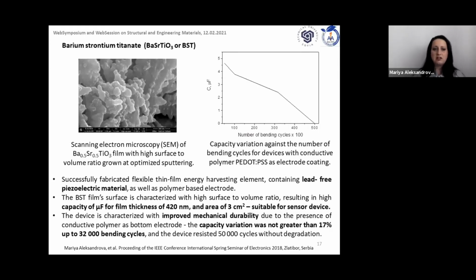The next promising material is barium strontium titanate. We found for this material that it is susceptible to nanostructuring if we grow it on a conductive polymer like polyethylene dioxythiophene. It is an amorphous conductive polymer. And such kinds of nanodendrite shapes are revealed, which reveal the total surface and increase the capacity. And although the total film thickness is again less than 500 nanometers and the area is 3 square centimeters, capacity in the range of a few microfarads was achieved.